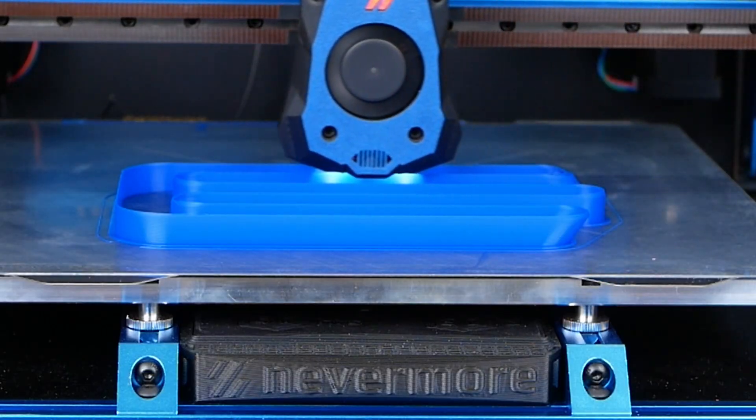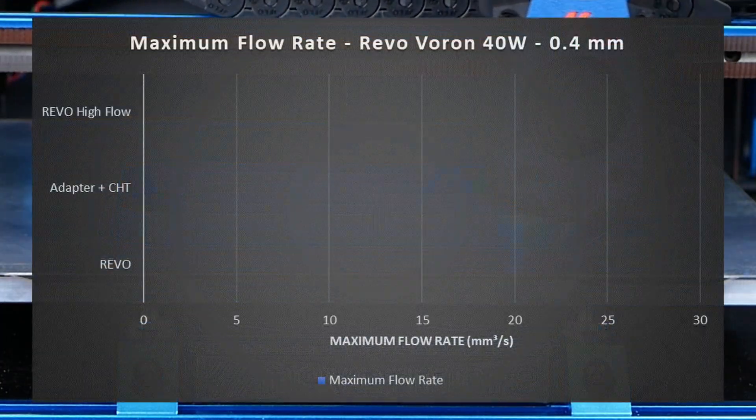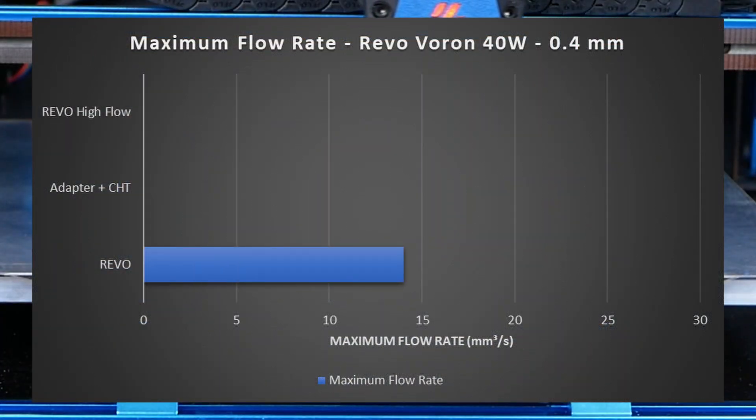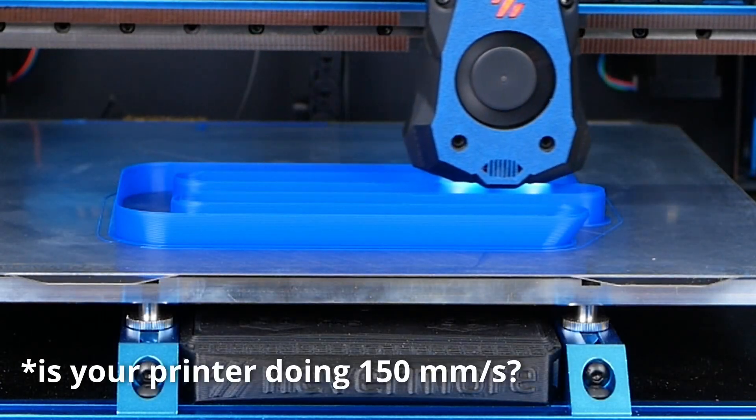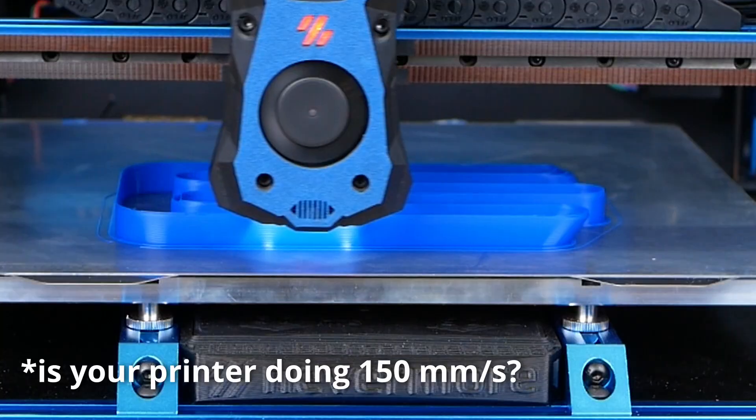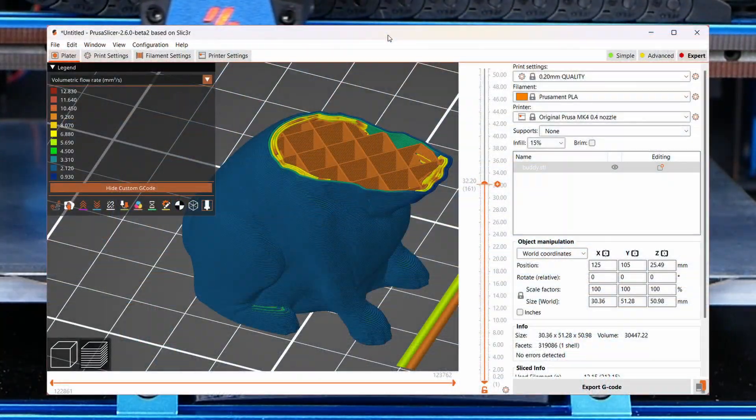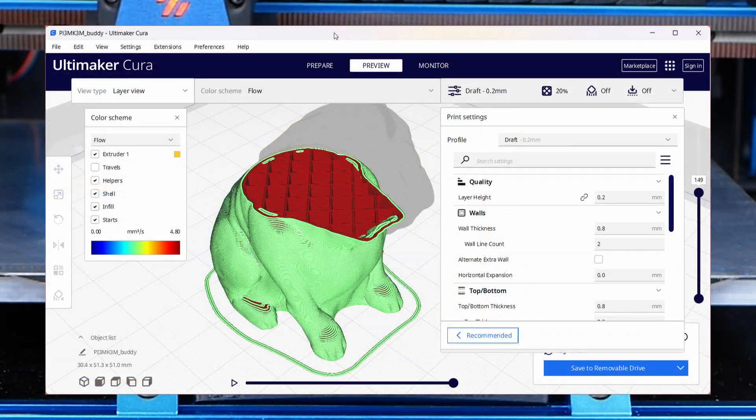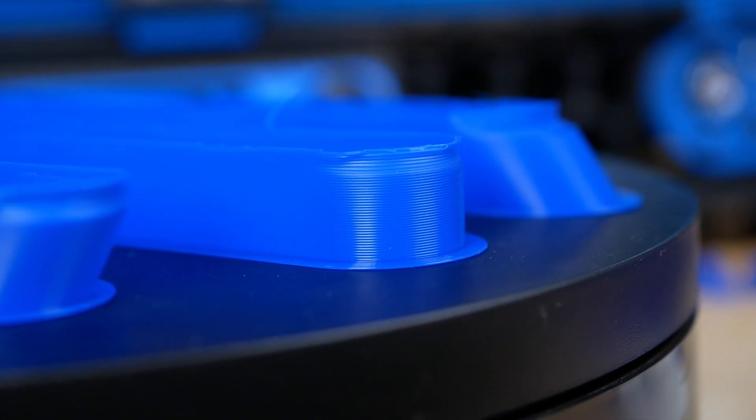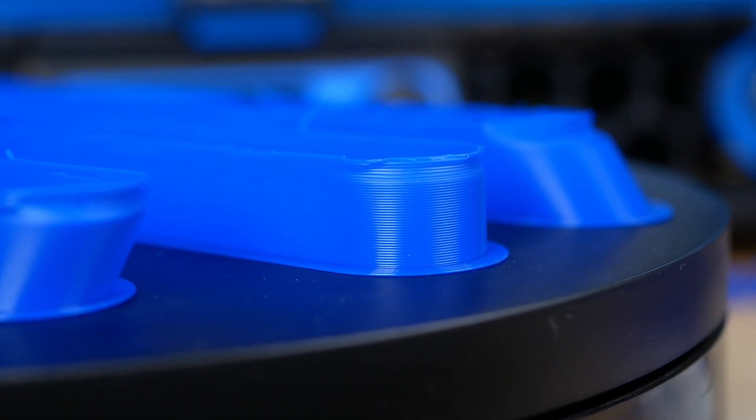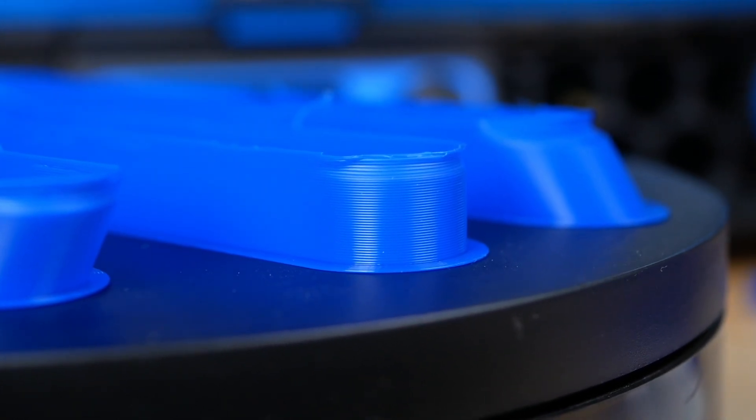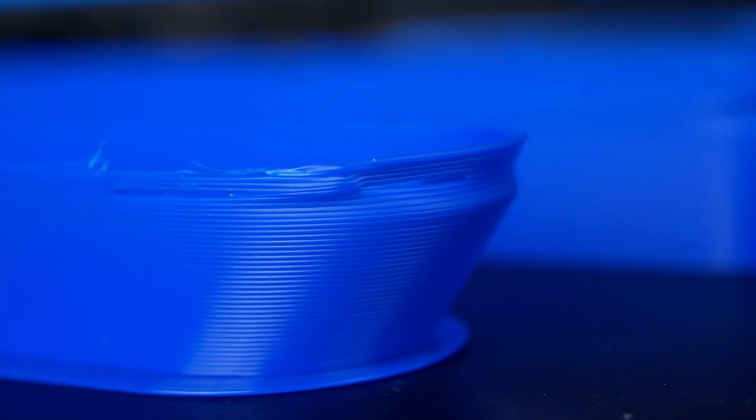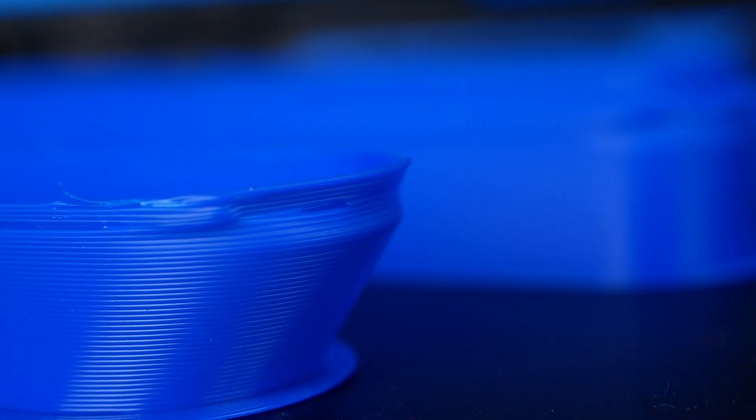Our reference, the normal REVO nozzle started misbehaving at 14mm³/s which would be around 150mm/s printing speed where you can already see that not everyone needs a high-flow nozzle. You can always check the flow rates of your prints in your slicer preview by the way. The failure mode is really interesting because we can see these bulge corners which is a sign of insufficiently molten material that's more like rubber when it leaves the nozzle and then contracts again, leaving you with this kind of phenomenon.